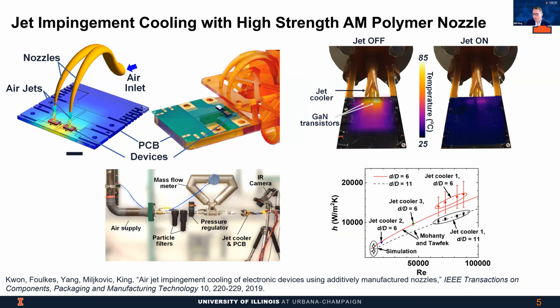Of course, the polymer is nearly as strong as a metal assembly would be, strong enough for the application, and it's also much lighter weight. So there are other benefits. Now, of course, the expense and complexity of the nozzle is not the only barrier for jet impingement cooling, but they are serious barriers, and we demonstrate how to potentially overcome them here.